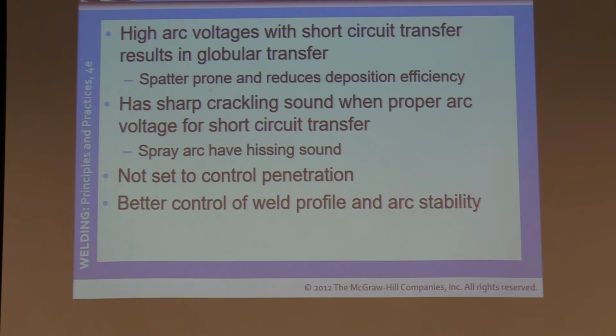So high arc voltages with short circuit transfer results in the globular transfer. Spatter's very prone, reduced deposition efficiency, okay? So if you start to see a lot of globular stuff, you want to make sure to back your arc voltage down. If you see a lot of spatter, possibly drop your voltage down one setting, keep your wire speed the same, and try that, okay?